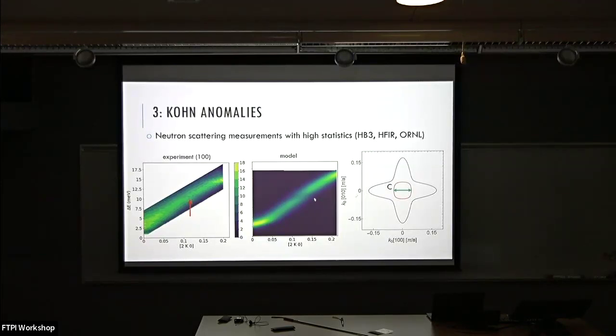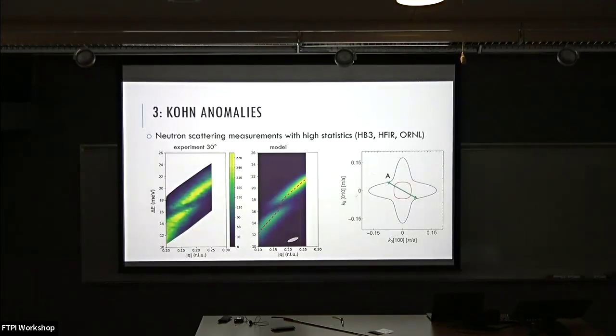And again, this is an attempt to simulate this. Similar to the other ones, this is roughly where you would expect it from the band structure. So we are pretty confident that we actually do see these anomalies. As I mentioned, for this C and the A, they're both intraband, so they should only be possible with a single phonon process. Which means, first of all, this is huge. It's partially huge because of the shape of the Fermi surface, but it definitely means that this large coupling is quite significant, and we should be able to extract the data.